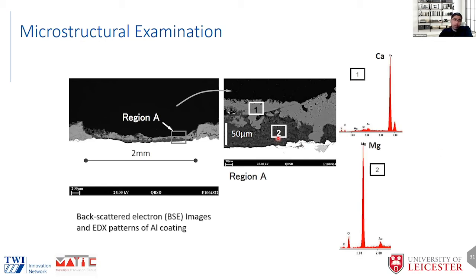In case of the layer close to the steel substrate, the darker region here in backscattered electron images, we can see it's predominantly magnesium, and we also detected oxygen in these layers. When we looked at these layers under SEM, we confirmed that the layer close to the steel substrate is magnesium hydroxide, or brucite, and the layer away from it is predominantly calcium carbonate, or aragonite in this case.